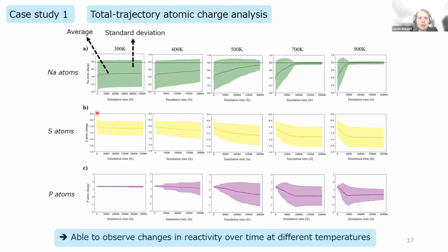For sulfur atoms, we see that there's an increase in the number of species. We have PS4 groups producing PS3 and so on, together with sulfide ions. And for phosphorus atoms, you can very nicely see an increase as well because of the production of these PS3, PS2, PS1, and so on groups. So by using Matlantis, we're able to get the approximate charge of every single atom over the entire simulation. And this allows us to compare how this system reacts at different temperatures, which I think is, you have to admit, a very impressive feat of the Matlantis software.